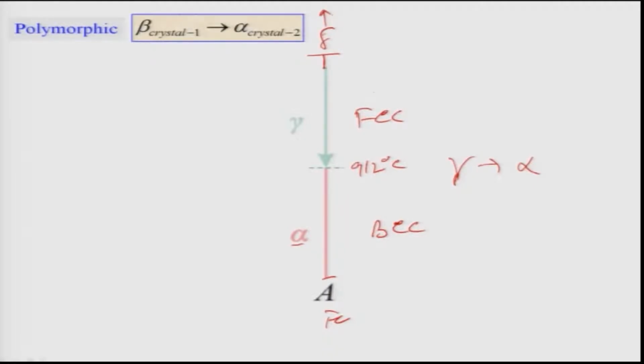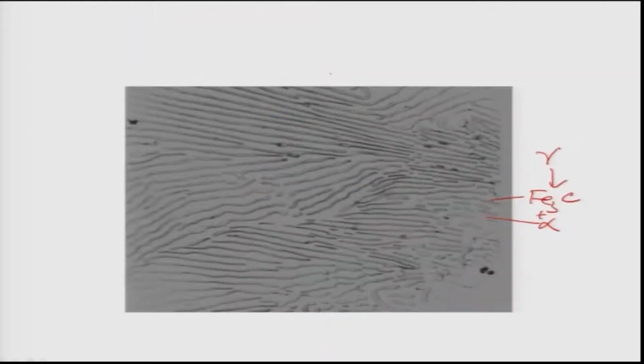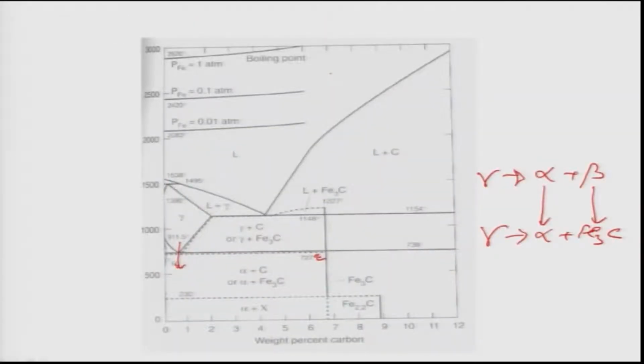So the important transformation for our discussion is between gamma and alpha, and this is for pure iron when there is no carbon. The moment we add carbon, things change. That is what is shown in this phase diagram. As you add carbon, the transformation which was happening from alpha to gamma at 912 degrees Celsius decreases. That is what is shown by this curve, which tells you that the transformation temperature of gamma to alpha, or alpha to gamma, is a strong function of the carbon concentration in the alloy.